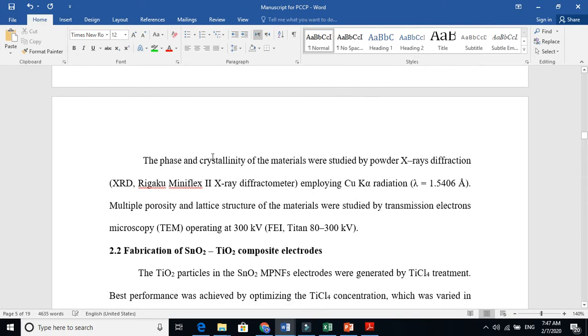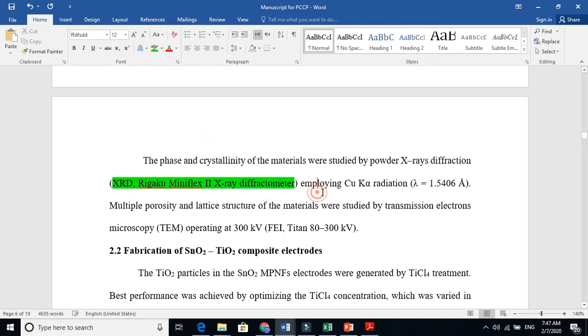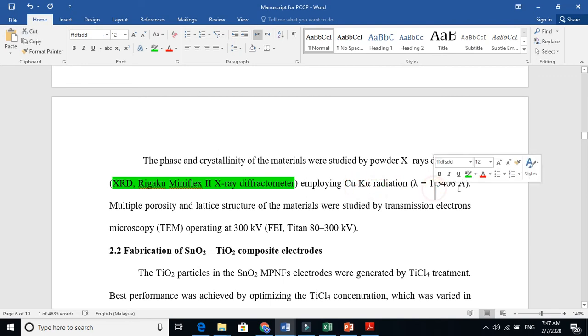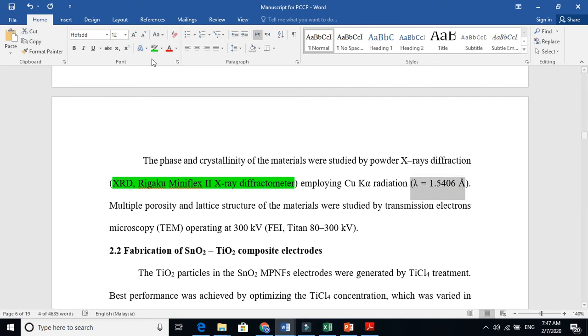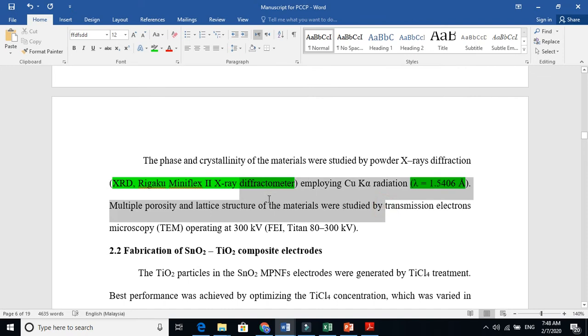The phase and crystallinity of the material was studied by X-ray diffraction. And I just give the name of that machine. The phase or the crystallinity of the nanoparticle, the nanofibers, were studied by using XRD using this copper K-alpha. The wavelength is 1.5406 angstrom. Almost one and a half angstrom wavelength. And we also further characterized this synthesized material by using transmission electron microscopy.